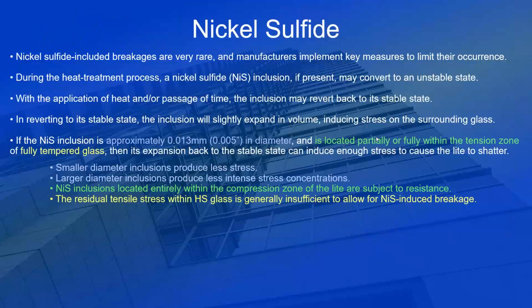So what is nickel sulfide or NiS? Basically, during the heat treatment process, the nickel sulfide inclusion, if it is present, can convert to an unstable state. Now, with the application of heat and or passage of time, warm seasons, colder seasons, that inclusion may revert back to its stable state. In the process of reverting back to its stable state, it expands in volume, which produces additional stress on the surrounding glass, which can cause that glass to break.